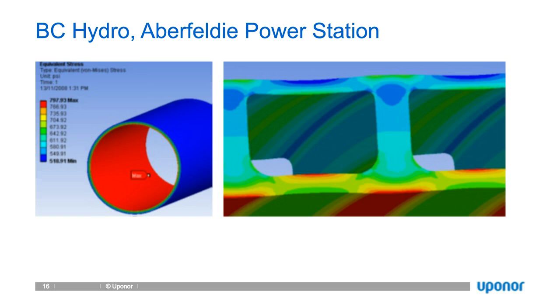We have here a picture of finite element analysis of both a solid wall polyethylene pipe and profile wall Weholite. For solid wall, the assumption of uniform pressure is actually only true for thin-walled polyethylene pipe. Polyethylene has a lower allowable stress than materials like steel, so the wall thickness, even for solid wall pipe, is considerably thicker than it would be for a steel material. The allowable stresses for polyethylene would be about 1,000 psi. For steel, could be 30,000 psi or more.